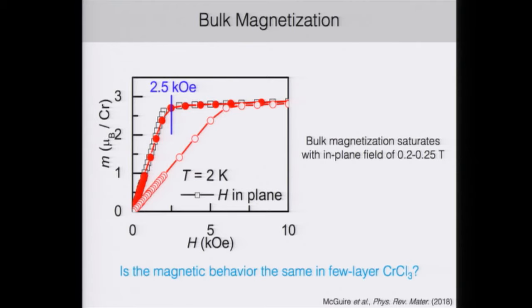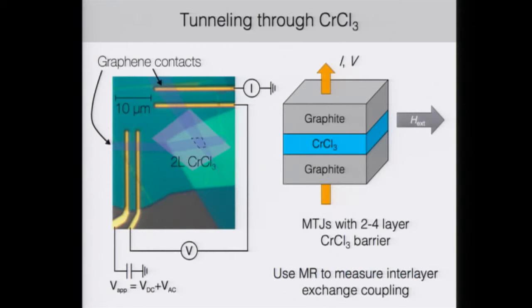So we wanted to ask the question, is this magnetic behavior the same as we take it down to the few layer limit? In order to study chrome chloride, we again turn to the magnetic tunnel junction as a way to probe its magnetic ordering. So again, we're going to use top and bottom boron nitride and 2 non-magnetic graphite electrodes, and then use the tunnel barrier, this time of chrome chloride, that's 2 to 4 layers thick. And this time, we're going to apply an in-plane magnetic field and use the magnetoresistance to measure the interlayer exchange coupling as we try to polarize this antiferromagnet to be in a fully aligned state with the magnetic field.